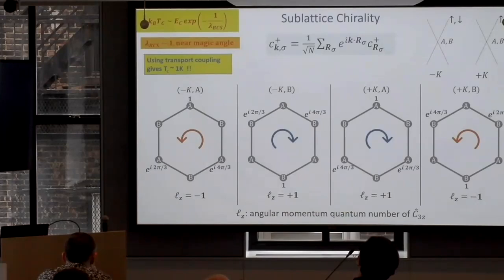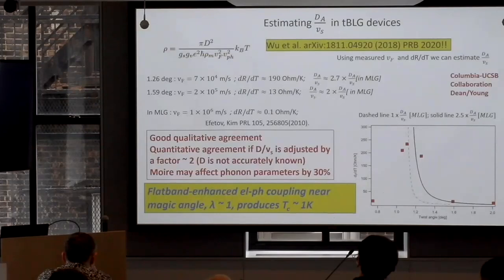Can I ask you this? How does in experiment Tc or superconductivity depend on the density of the carriers? Well, I already showed you the doping. It depends on the doping. So at some dopings there is no superconductivity, at some doping there is superconductivity. But generally, should I think about the density of the carriers to be small when there's superconductivity, or can it be sample dependent? It depends on the sample. Very small, there is disorder, because very close to the cone. Basically, in our picture, electron-phonon superconductivity is everywhere. It has some dependence on density, but not very strong, because this theory that I'm showing is very simple. It does not include all the Van Hove singularity. Maybe this question is better addressed when I show you more results.